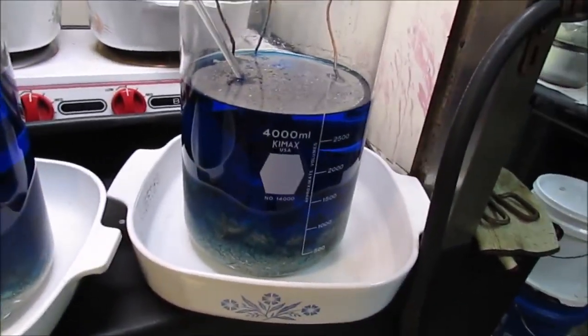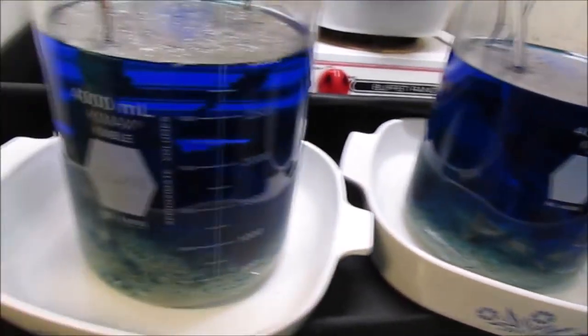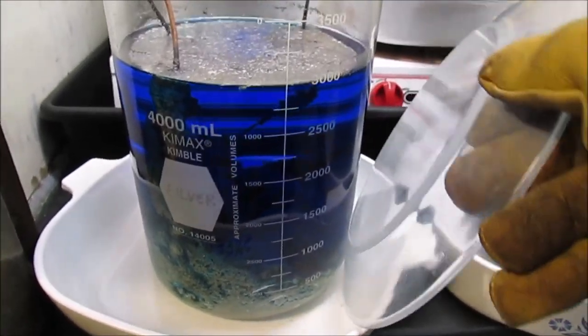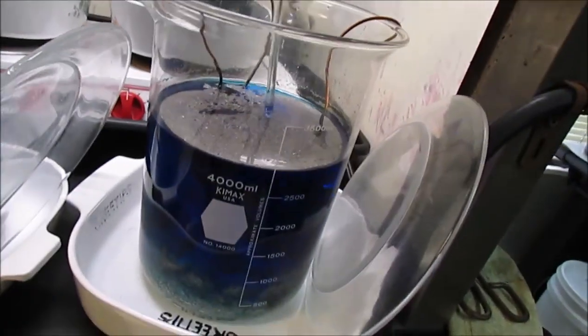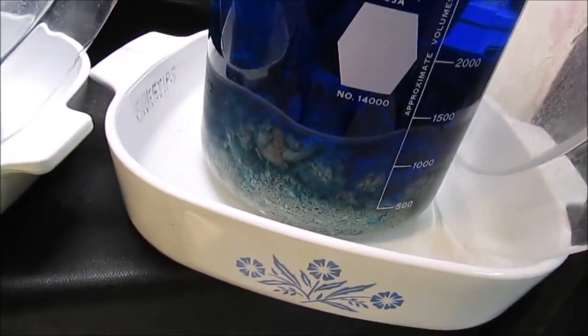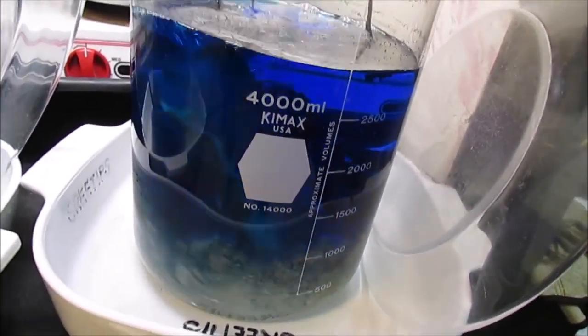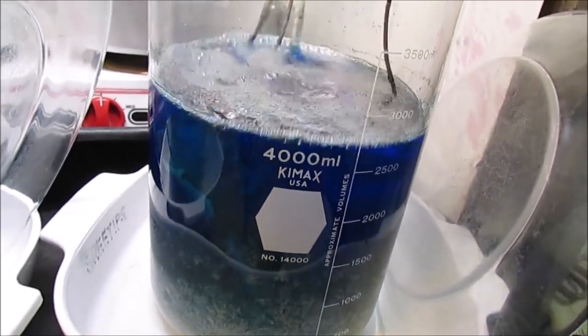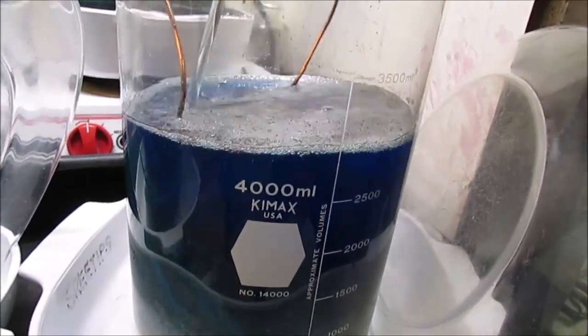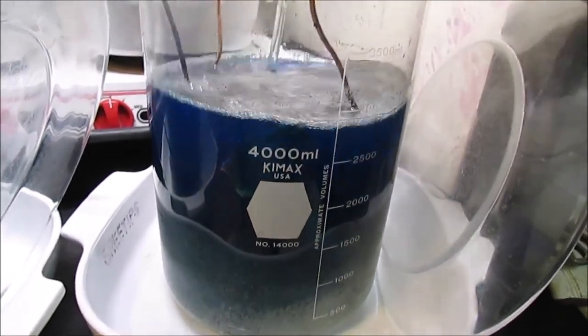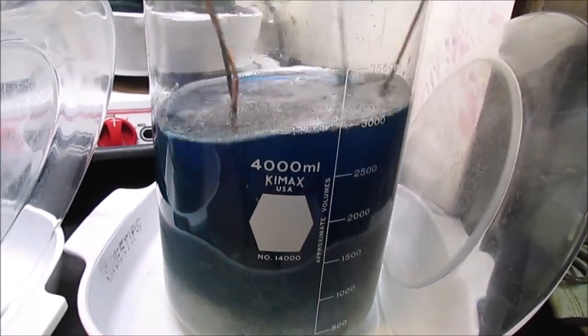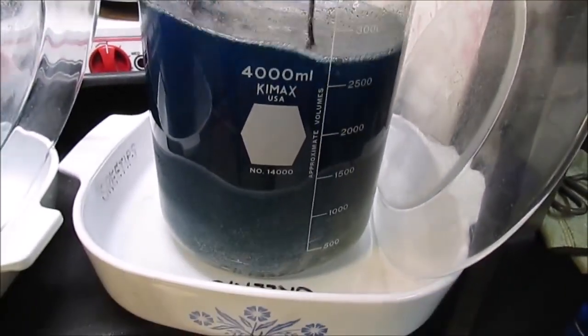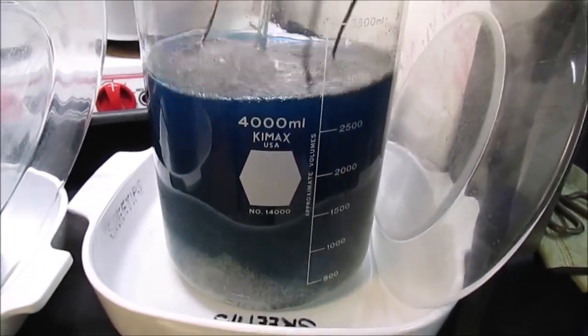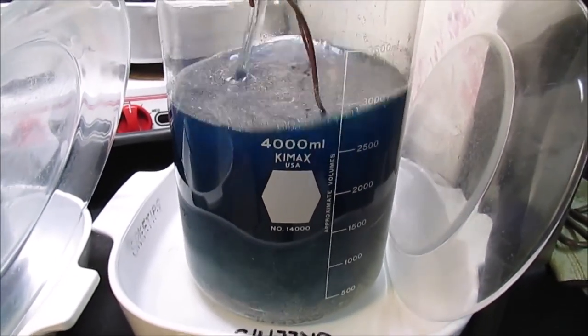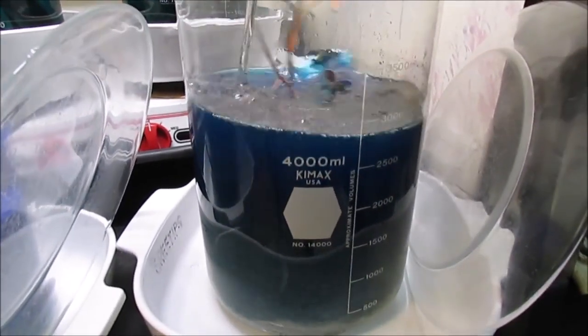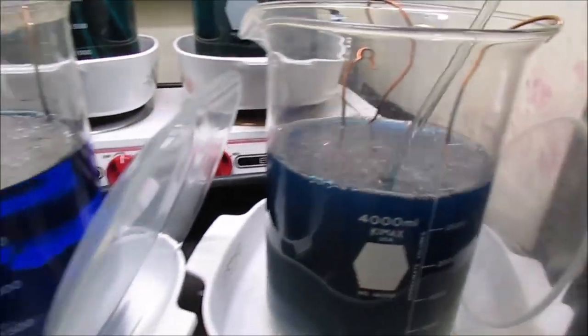Now I'm going to turn my attention to the cement silver here. It's been allowed to react overnight. Go ahead and stir this up. The silver down here in the bottom of the beaker will tend to trap some of the silver nitrate solution, so I want to stir that up real good. Make sure to get any silver nitrate solution that's trapped down inside the cement silver at the bottom. Release that so it can come in contact with the copper and get all the rest of the silver cemented out.